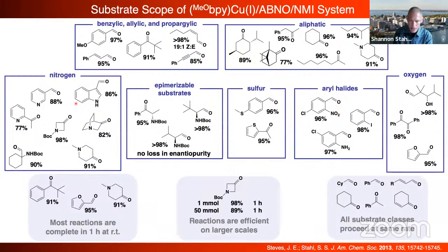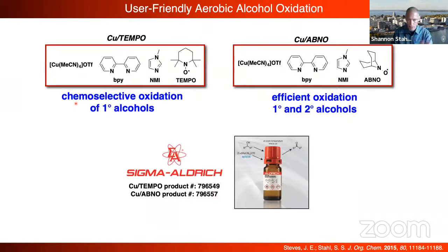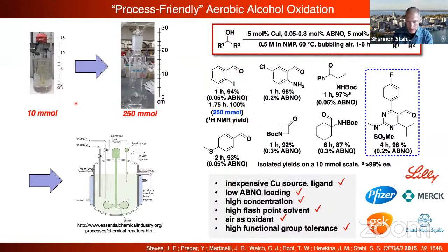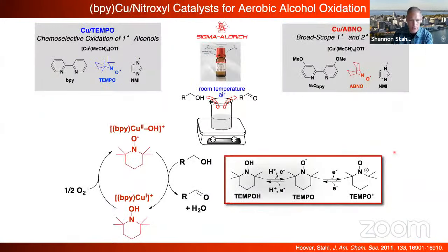And yet this chemistry is very compatible with these substrates, which is part of the appeal and why the medicinal chemists were clamoring for a solution that they could just buy where they don't have to weigh out all the individual components. And so we ended up doing that and selling it through Sigma Aldrich. It's also been scaled. So a number of companies have now publications, but also anecdotal comments from companies that they can scale this because it really is a mild reaction and is compatible. You can dramatically lower the ABNO loading, for example. This was a paper we published in collaboration with several companies focused on the process features.